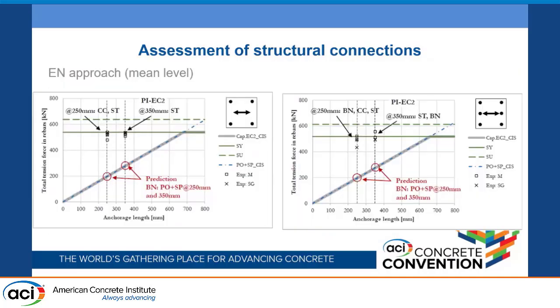So if I now show you the comparison, again given in the thesis by Vinay Mahadik, of what would be the failure load predicted by the current Eurocode approach at mean level. The failure load predicted would be rather small here, and we would always assume a pull-out failure because we consider it as an equivalent cast-in bar, but the actual failure loads were much higher.